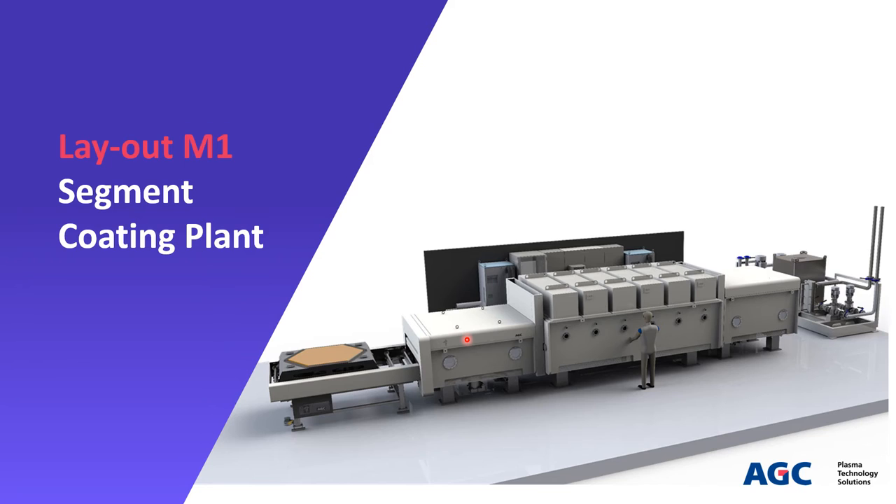Next, the mirror segment will be transferred to the load lock chamber, which is the only part that is not continuously under vacuum. It is separated from the atmosphere and the main process chamber by an isolation valve. The main process chamber is designed for DC and AC magnetron sputtering processes in sputter-down arrangement in reactive and/or metallic mode. This chamber includes six compartments, all fully equipped and ready to receive a cathode. In principle, three cathodes would have been sufficient to make the Gemini stack; as such, the coater will allow making more complex stacks during future upgrades. The overrun chamber is adjacent to the main process chamber. The total length of the coater is about 9.5 meters and the coater width is about 2.5 meters.